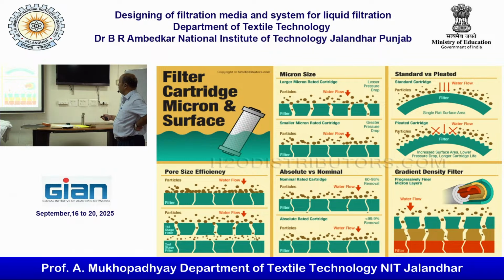Here, if you want to remove large micron rated particles with the cartridge, then there is lesser pressure drop. If you are going for a smaller micron rated cartridge, there is greater pressure drop. That I have explained already. Another aspect is absolute versus nominal rating. Nominal rated cartridge means 60 to 90% removal of a particular size. That is known as nominally rated. Whenever I say absolute rated, that means it will be 99.99% removal. Absolute rating is possible in the case of woven fabric, as I told, whereas non-woven fabric can be used for nominal rated cartridges.